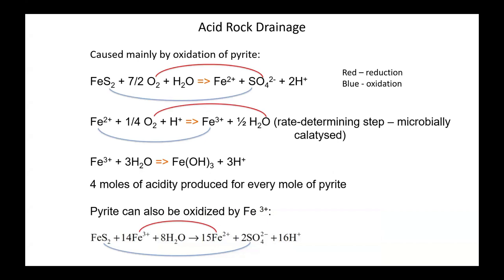So acid rock drainage is due to oxidation of pyrite. Basically, there are a few other minerals we'll talk about briefly. When pyrite forms under particular conditions, such that when it's exposed to oxygen at the Earth's surface, it alters quite quickly, and it's a redox reaction. So the sulfur in the pyrite oxidizes to sulphate, and it's oxidized by oxygen, which is itself reduced to the oxygen in the sulphate molecule. The Fe2+, the ferrous ion that's produced by that, is then oxidized to Fe3+. Again, normally by oxygen, which in this case is reduced to water.